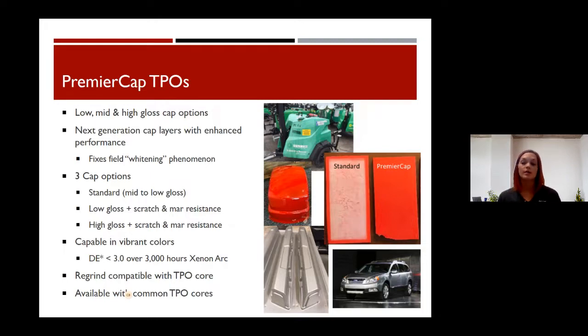Like I said, all of those can be extruded alone, or for properties, we can extrude a cap over them. Our Premier cap line is relatively new. We obviously have a standard high gloss cap, but we developed the Premier cap, with low, mid, or high gloss options. It came about to address a field whitening phenomenon that was happening with TPOs. You can see that light tower, the green there. It looks like a weathering failure. It looks whitened from being outside. It's not the bright green anymore. It seemed to only be happening after thermoforming. And like I said, it looks like a weathering failure.